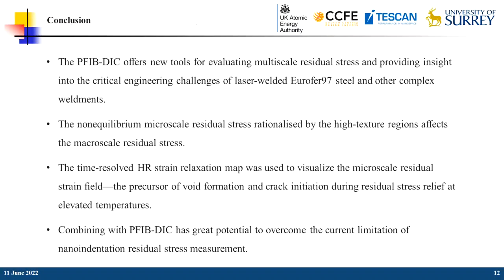In conclusion, our analysis of microstructure and the residual stress distribution in laser-welded Eurofer97 steel using a number of advanced microscopy techniques, for example EBSD, PFIB-DIC, and nano-indentation, really offers new tools for evaluating the multiscale residual stress. Our approach has provided insight into the critical engineering challenge of the laser-welded Eurofer97 steel.